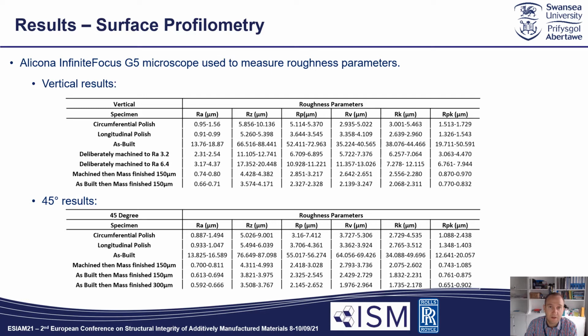So moving on to the results. Firstly, looking at the surface roughness values, considering the vertical specimens given in the top table. As we can see, looking at the Ra values as the main parameter here, the as-built specimen has the largest value, so the worst finish, or the specimen with the highest average of absolute values of the profile height deviations from the mean line. This is then followed by the deliberate Ra finish of 6.4, then 3.2, then the remaining 4 finishes are quite similar. This is very similar for the 45-degree samples, where again the as-built samples have by far the roughest finish, with the rest of the finishes behaving relatively similar.